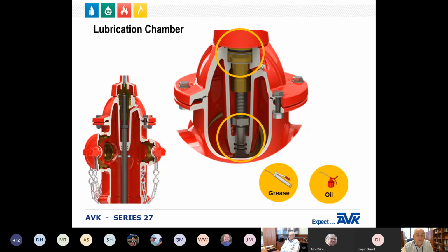If water somehow does get into the lube chamber and mixes with the lubricant, it can mix with the acetate and form acetic acid, which is very corrosive to iron and mild steel. However, acetic acid is not corrosive to stainless steel.